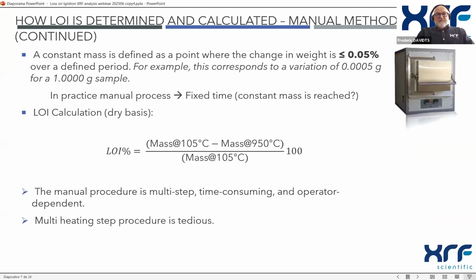When we use the manual method, we of course need to be sure that we reach the constant mass. When we speak about constant mass, it means that the change in weight is below 0.05%. So it means 0.5 milligram in a sample of 1 gram. But when you use a manual process, of course, you are never sure that you reach constant mass.